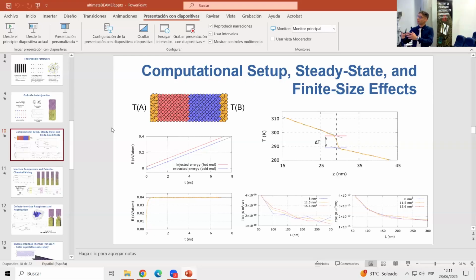We are describing a system which is fundamentally out of equilibrium, and you could use some more sophisticated thermostating techniques, where you couple the system to another system, a reservoir, and then you solve the full equation of motion, so energy is strictly conserved. You're not introducing any numerical modification to the solution of the equation of motion, but still that would have been completely meaningless in this case because you are only interested in the interface zone. There is a result, I haven't mentioned it here, probably from Ricardo, which shows that the thermal boundary resistance is a property of the interface. It only depends on the interface. So as long as you can neglect what is going on far from the interface, you're fine with this. And this is why we have taken this. It's one of the most standard means of tackling the thing.